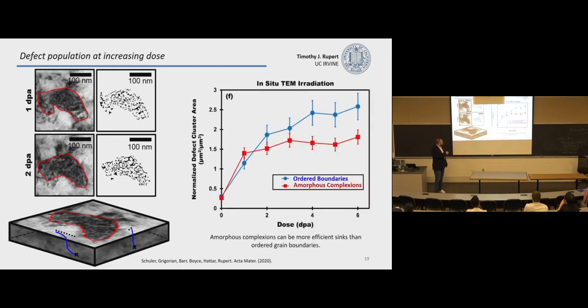So this is the defect cluster area as a function of dose. And what you'll see is that the sample with the amorphous complexions is below the one with ordered grain boundaries. So that's a good sign. It means we're damage resistant. And more importantly, is this sort of change in the slope. So the damage is building up much, much more slowly in these materials.